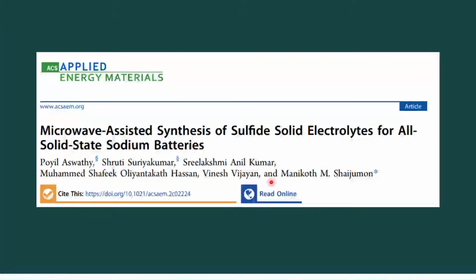So the last part is microwave assisted synthesis of sulfide based solid electrolytes for all solid state sodium ion batteries. This is my project work. I will have to tell you a story about it actually. When I was writing my proposal, I looked into a few papers and found that Na3PS4 is an ideal soft candidate. You don't have to go for high temperature sintering. You just take the precursors for Na3PS4, which are sodium sulfide and P2S5 in a stoichiometric ratio, mix them, ball mill them and you get the powder. I felt it was so easy, and I thought I could go ahead with it easily.